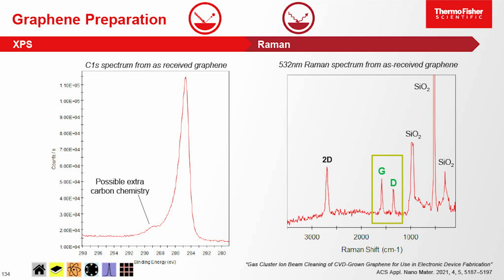So the G and the D bands are the ones I'm going to concentrate on. The G band is representative of the actual quality of the film. So if it's good quality, you just see a G band and you don't see a D band. The D band is indicative of any defects you might have in that hexagon graphene structure.